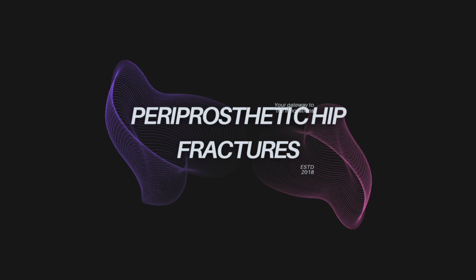I'm not convinced by that line of reasoning because cement in cement introduces severe biological risks. Namely, cement extrusion into the fracture site, which physically inhibits bone union. But how much of an issue is that, really, if the stem is offloading all the weight? It is a huge issue. When you pressurize new cement into the femoral canal to hold the new stem, those high pressures can force polymethyl methacrylate, the bone cement, directly into the fracture lines. This does 2 very destructive things. First, the curing cement gets incredibly hot, creating a zone of thermal necrosis that kills the surrounding bone cells.